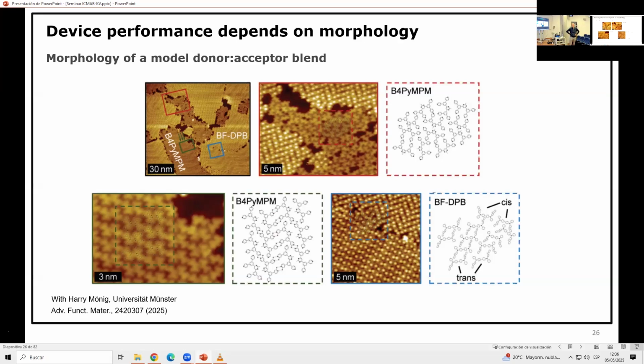We started working recently with STMs, which are getting very good. With some tricks, you can actually see the molecules, even in scanning tunneling microscope images. So we use something not so typical for solar cell materials, but something we could image very well. It's a blend of a donor and an acceptor, only a monolayer in this case. There you can see how the morphology looks at the nanoscale or even the molecular scale. This was a material which was very good in converting the absorbed photons into charges. You see it packs, with some type of order, but it's not a big crystal, it's really mixtures. There are some amorphous regions in there.